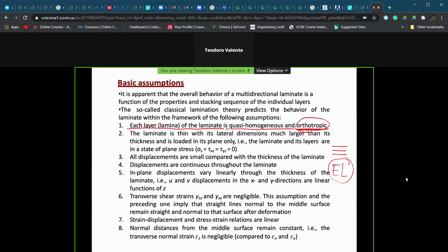is that we can accept a continuous variation of the displacements through the laminate. That is, we cannot accept a discontinuity in terms of displacement, that is, in terms of strain through the laminate, because otherwise we have broken the interface between two adjacent lamina.